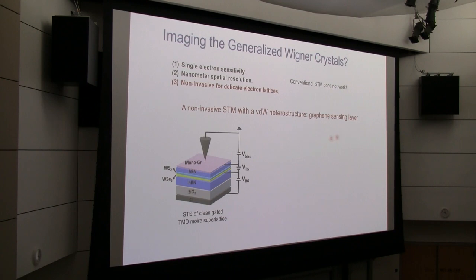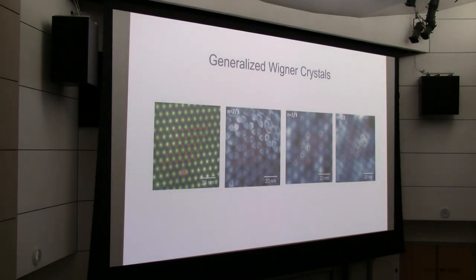So we actually create a system shown over here. In addition to this WS2, WSe2 Moire superlattice, we add a very thin BN, a few nanometers thick, and put another monolayer graphene on top of it. So the top monolayer graphene acts as our sensing layer. The STM actually tunnels into graphene, so it doesn't disturb the Moire superlattice strongly. And to understand this, in a somewhat hand-waving way, we can imagine like this. If there is an electron lattice, coming from, say, a generalized Wigner crystal, sitting in the Moire heterostructure, the periodic electron lattice will change the potential in this monolayer graphene. And when you do STM imaging of the graphene, you will see basically a periodic structure that maps the underlying electron lattice. And this scheme actually works quite well.